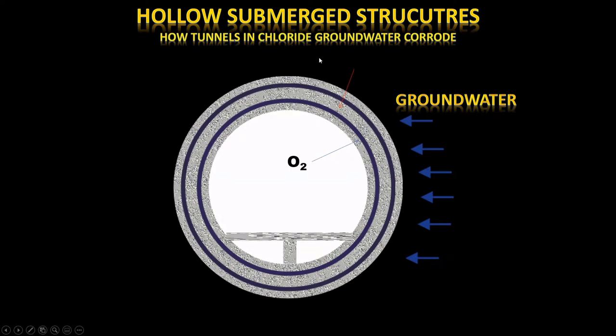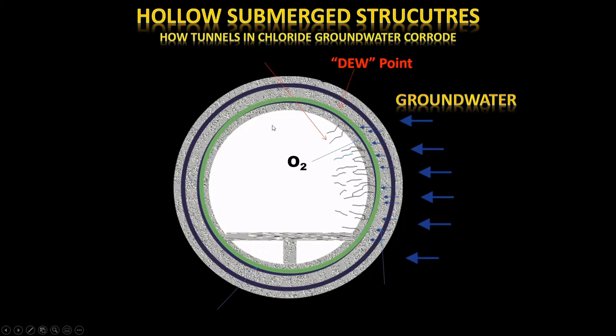Well, basically, just to simply explain that, groundwater is going into the tunnel containing chlorides. It's diffusing through the concrete, penetrating through the concrete until it reaches the dew point, which is just at the face where it evaporates into the interstitial space in the tunnel. It's also sucked through with a piston effect of traffic going through the tunnel. What then happens, the water evaporates, but the salt stays in the concrete and slowly will start to diffuse back to that inside reinforcement, and that is the one which will corrode.